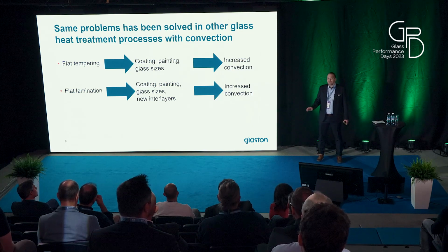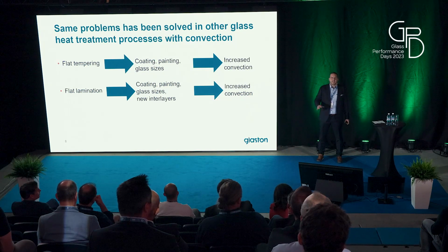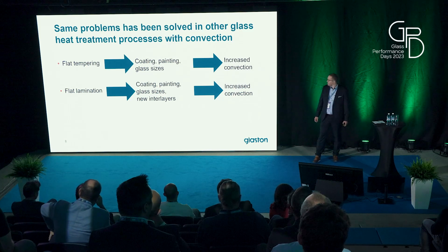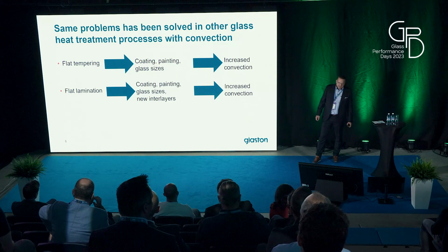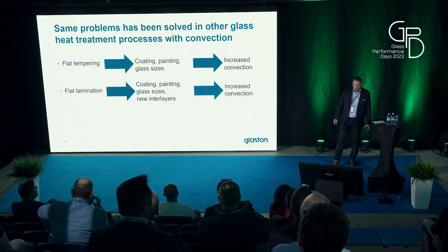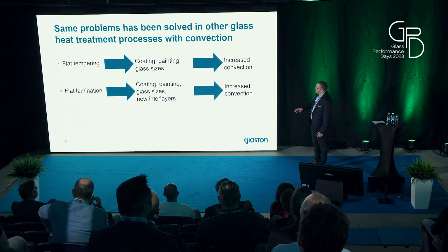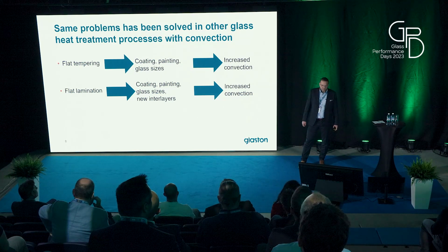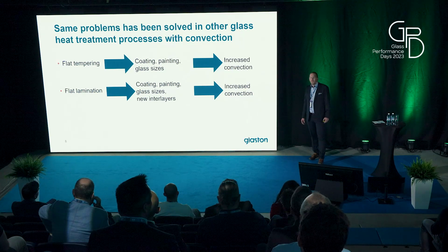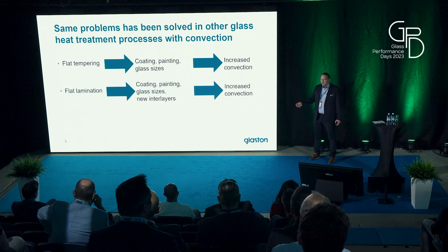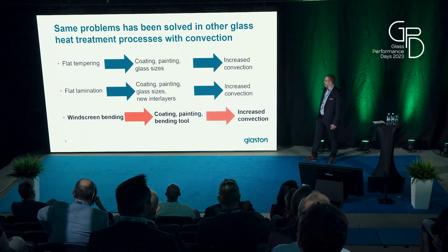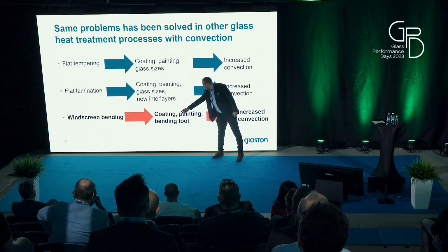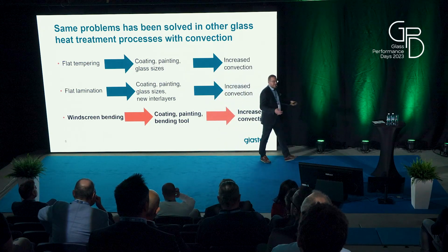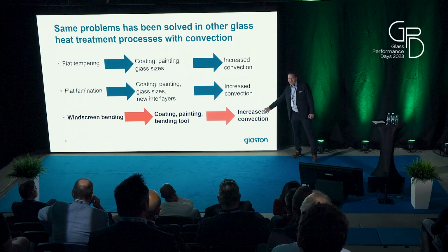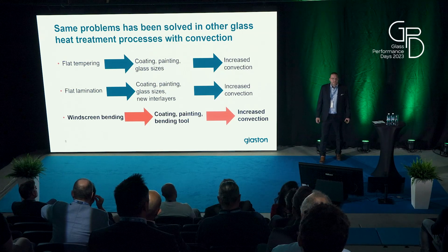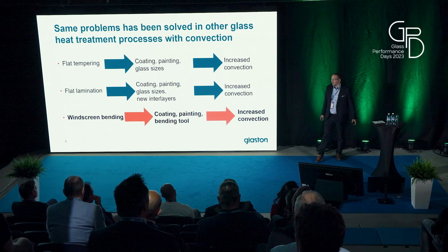balanced glass temperature around the glass area, and to make this heating so that the glass has a uniform temperature during the process. We increase the convection to make this uniformity better. And also the controlling of heat transfer. And now in the windscreen bending, because of coated glasses, painted glasses, and there's also the bending tool which has an effect on the heat transfer, with increased convection, we can now do this heating part more uniformly to get better results for the end result.